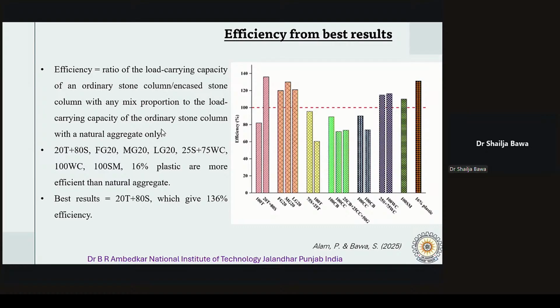So this graph here shows only the best results obtained by various waste. From the different studies where we got the maximum load carrying capacity, we used that percentage of that waste, that this particular waste at this percent gives us the maximum density, maximum load carrying capacity. Okay, so here you can see that 20% tires with 80% of natural aggregates, and replacement of fine, medium and large size tire by 20%, 25% waste concrete, 100% waste concrete, and 100% silica manganese slag. These are more effective, and 20% tire with 80% natural aggregates, that is the best result.